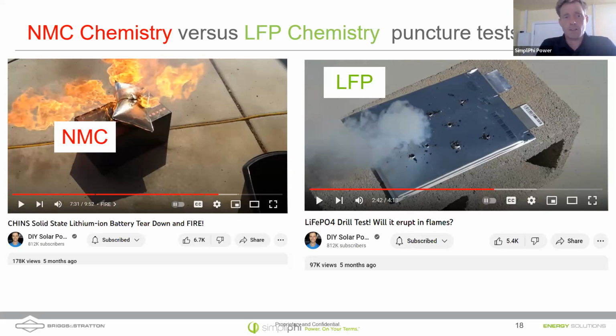I'm showing you the screenshot here from his video, but I'll have that link here and you can go and watch that video yourself. In comparison, he took a pouch cell with LFP chemistry and drilled holes in it. He had to drill almost 10 holes before the thing even started to off-gas. Finally, it did off-gas, but as you can see, if you watch the video, this is basically all you get, a little bit of smoke. It's a much longer, slower release of energy from an LFP off-gassing event.